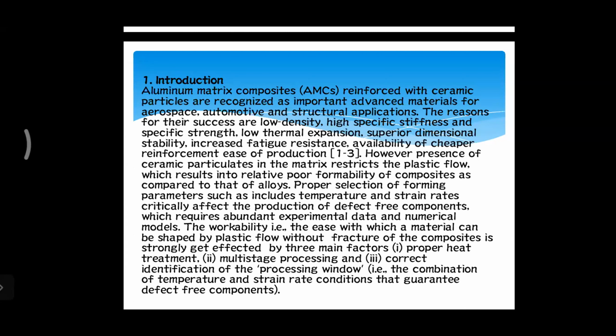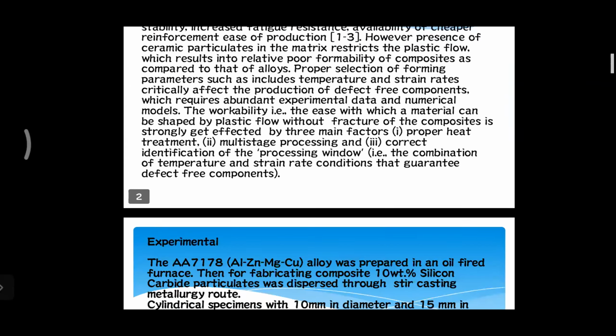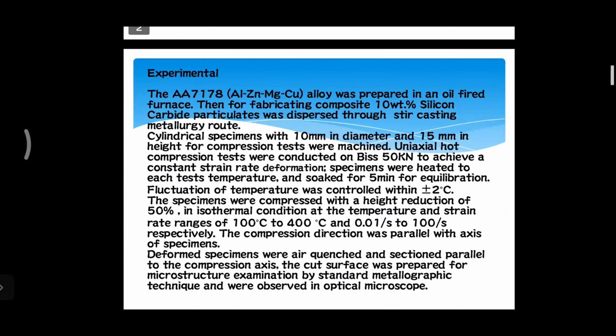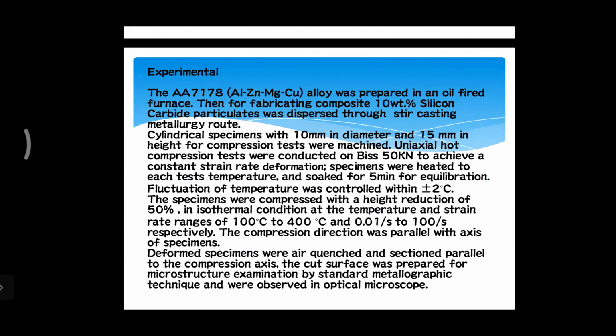So we are making the aluminum alloy applicable for engineering applications by introducing a 10% SiC composite. We have to find where the material is suitable for working, so we have to do the hot deformation of it. For the experiment, we used an oil-fired furnace. We prepared the material and used the BIS 50 kN hydraulic machine for the compression test.